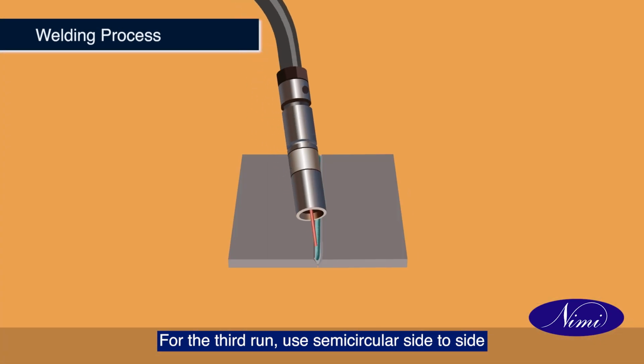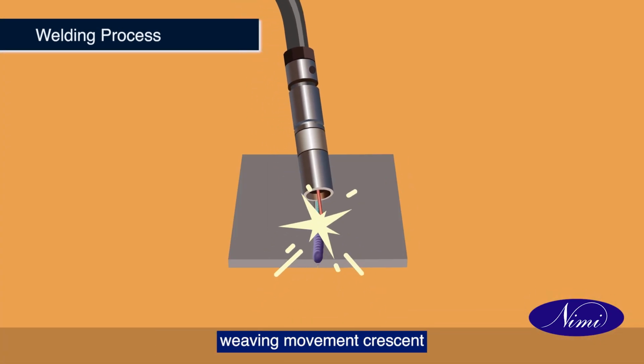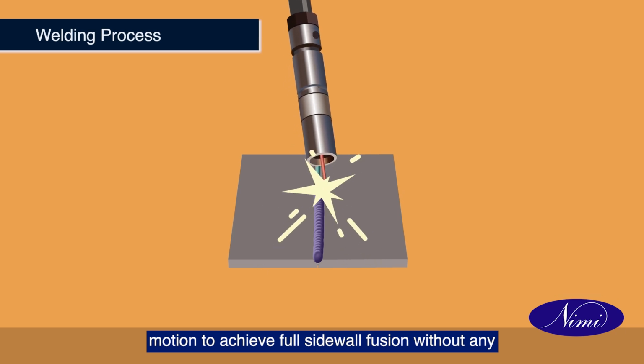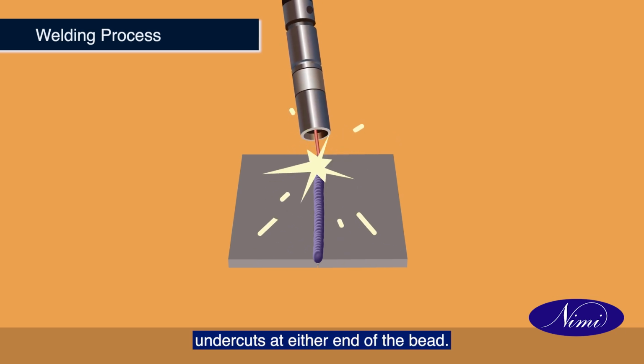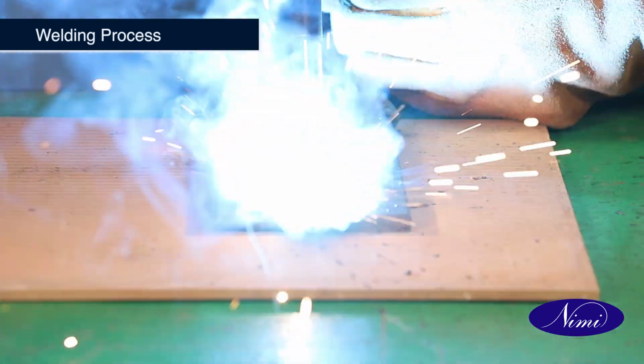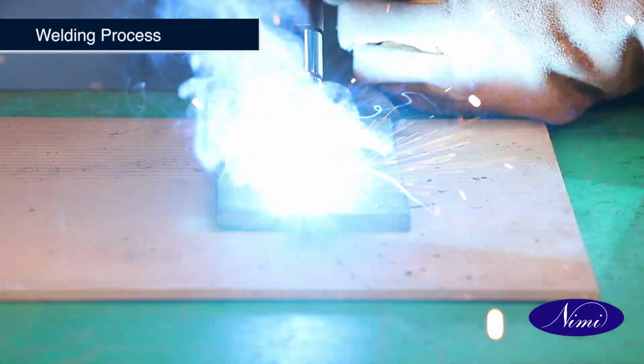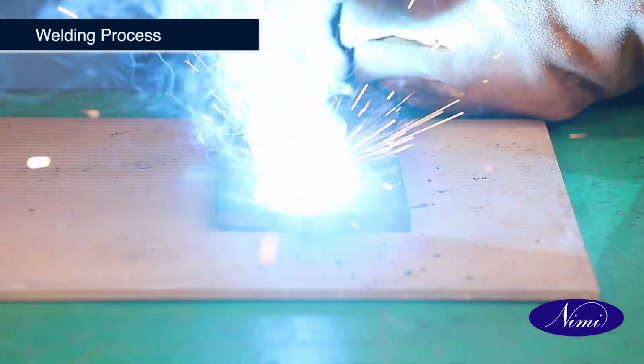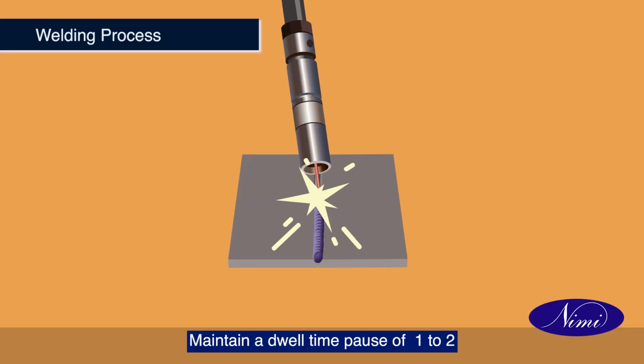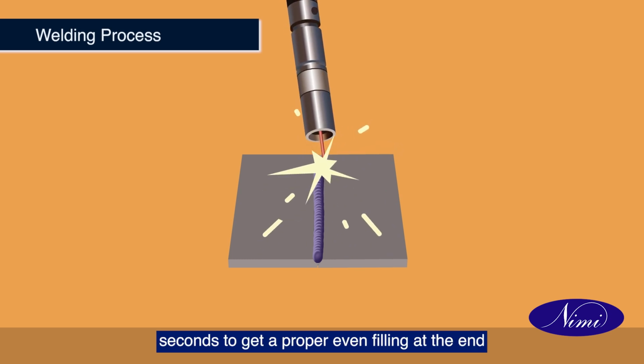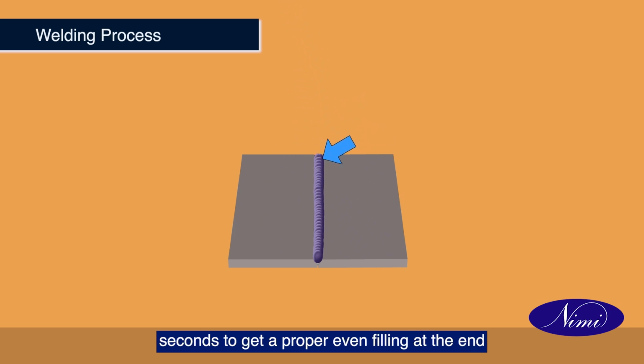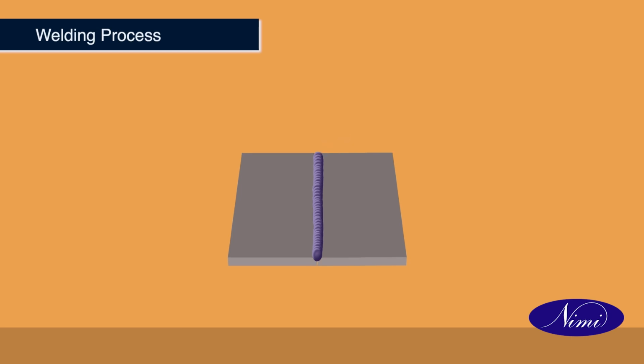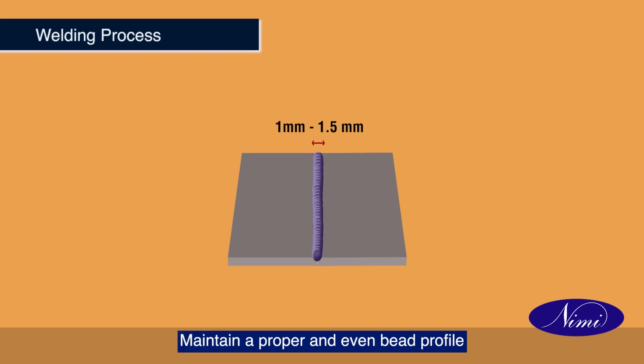For the third run, use semicircular side-to-side weaving movement, crescent motion, to achieve full sidewall fusion without any undercuts at either end of the bead. Maintain a dwell time pause of 1 to 2 seconds to get a proper even filling at the end of the toes on either side of the bead. Maintain a proper and even bead profile and a reinforcement of 1 to 1.5 mm.